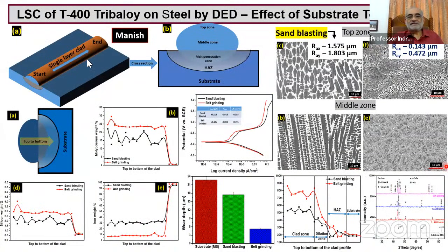One other important aspect, while you deal with this, then you graduate. This is Manish Naik's work. If you compare these pairs of microstructures, the one on the left and the right, same material, same cladding routine, same parameters, absolutely everything the same, except the state of the substrate prior to cladding. This one was sandblasted and this one was subjected to belt grinding. Sandblasting causes more roughness and hence more scatter and more laser absorption. So interdiffusion or intermixing of the clad and the metal is fairly large. So this melt penetration zone is thicker in the sandblasted samples, whereas after belt grinding you don't have so much roughness and hence laser coupling is low.